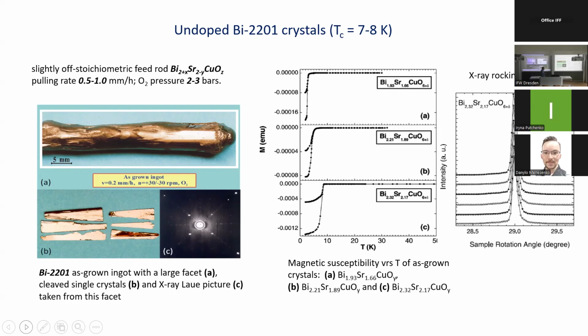Here you could see a typical as-grown ingot. In the end portion, you see a very nice, very large facet. Here, the Laue picture taken from this facet. And single crystals that were cleaved from this ingot. The crystallinity is quite good if you look at these X-ray rocking curves. The main drawback of this system is that some of these crystals are superconducting, others not. And still we don't know why, because we do not see any difference in composition or in structure.